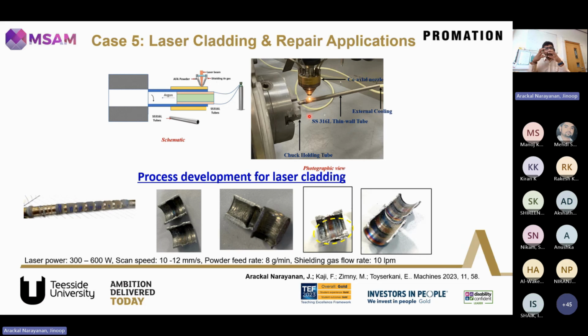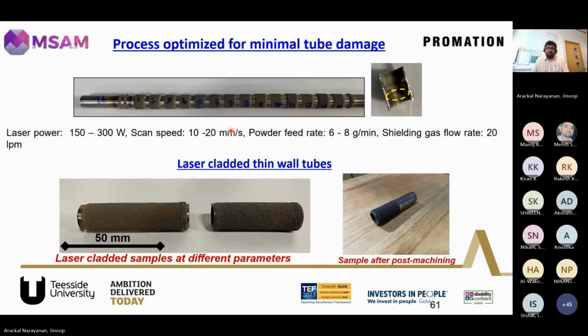So we had to develop a process of external cooling, and we did a lot of trials. We damaged the tube a lot with the initial trials, but as we moved forward, we could optimize the shielding gas flow rate and control the cooling, because when the laser touches the surface and it is only 0.5 millimeter thick, the tube gets damaged within a second. So it's very important to have very fast cooling and a very fast scanning speed as well, because we should not allow the laser to react at a particular point for a longer period of time.